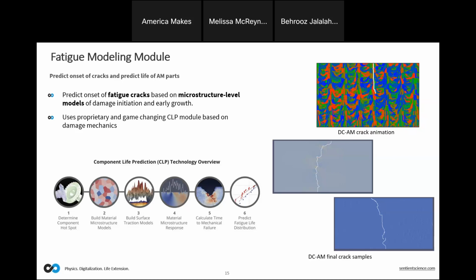On the left-hand side, I'm showing again that component life prediction technology. As I mentioned, it is patented, and it is based on damage mechanics, and it is not based on fracture mechanics. I like to emphasize that, as a lot of other computational packages that are providing the fatigue life work with fracture mechanics methodology, which is different than what we use. Again, we are using damage mechanics. The biggest advantage of the damage mechanics method compared to fracture mechanics is you do not need to have any initial crack in your model to start from and see how that crack is going to propagate and how long you have until the failure.